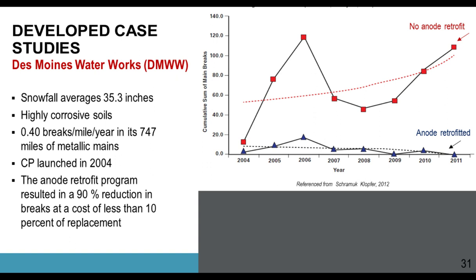They started launching their cathodic protection system in 2004, and in the graph on the right, you see the red dots are the number of breaks and projection of breaks for the pipeline with no cathodic protection, and the blue dots show after they installed and launched their CP program in 2004. Their conclusion from their CP analysis and CP program was that the anode retrofit program resulted in 90% reduction in breaks at a cost of less than 10% of their replacement.